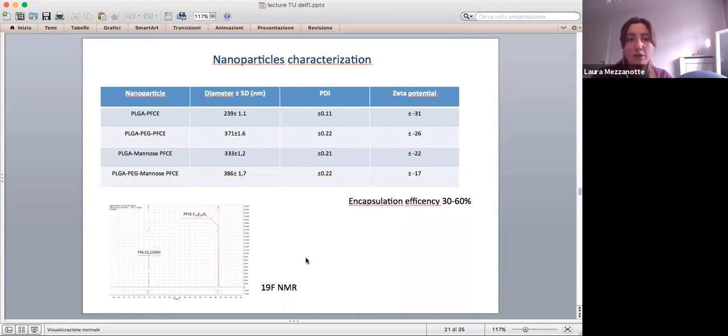The difficulty here is that PFC is that type of compound that is soluble in nothing. So we have to homogenize PFC before, and then we do an organic phase with PFC and the PLGA. And then we do a water phase containing polyvinyl alcohol, one percent. And then little by little, we add the organic phase to the water phase and we do magnetic stirring. And then we do ultra centrifugation to purify it. And then later, we also do freeze drying to really purify them better. And then we get this nice round particle that we analyzed at TEM. And we produce different types. So in the studies we did, for example, standard PLGA with perfluorocarbon, PEGylated ones, and then the one targeting and non-targeting mannose.